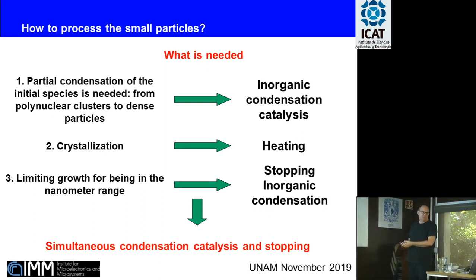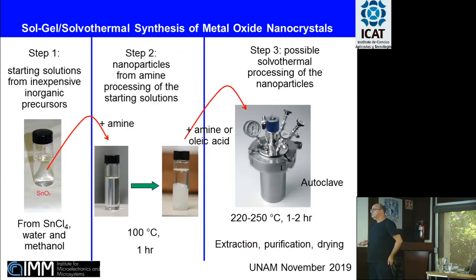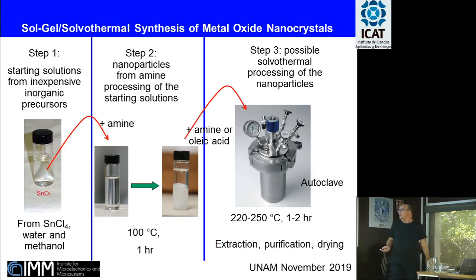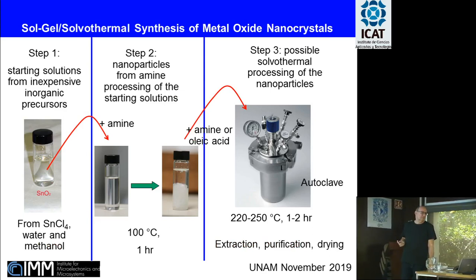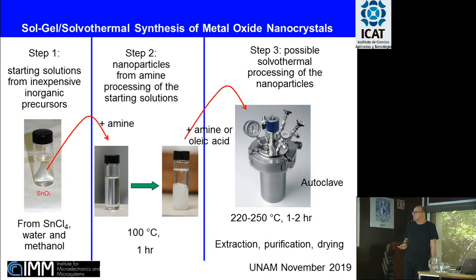Because we have two contradictory aims. We have to do some Sol-Gel process to make these small particles grow a little bit more by condensing them. But at the same time, we want their growth to stop at a certain point. How to do this? It is very easy. The procedure is extremely simple. We have our starting solution. These are the same that we prepare for thin films, exactly the same. We make a precipitate into an amine at room temperature, and then we make a heat treatment at 100 degrees C.